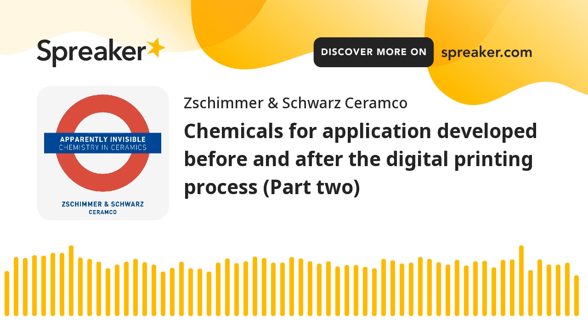What happened in this case? As we know, the tiles that, thanks to the conveyor belts, reach the printing machine are usually covered by a superficial layer of glaze that is marked by a high water amount. These tiles, and this is the second element that we must consider, have a temperature that normally ranges from 50 degrees to 60 degrees. This particular combo, water plus high temperature, can be a serious problem. In fact, the water vapor that is formed tends to accumulate on the metal parts of the printing bars until the formation of drops. And these drops, of course, may fall on the tile, causing significant damage.